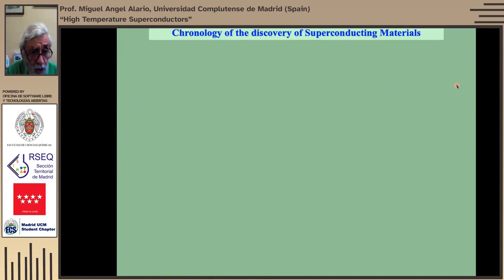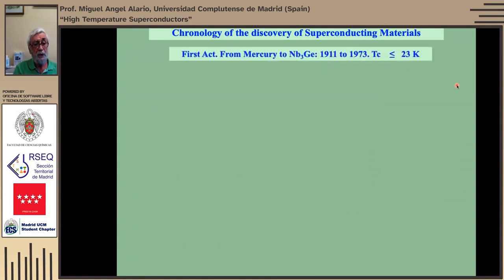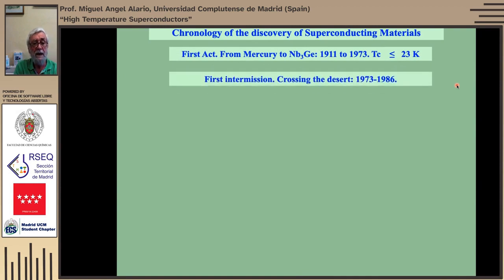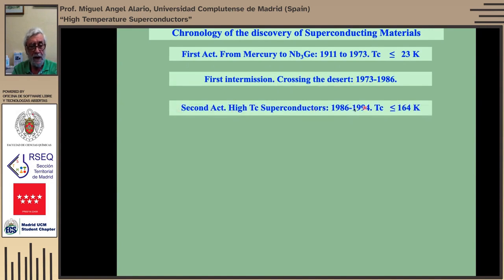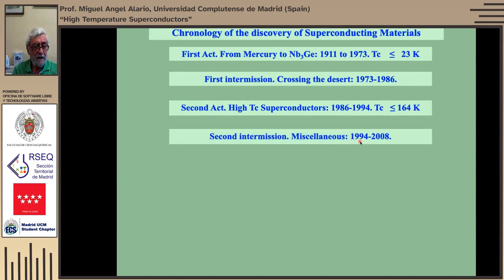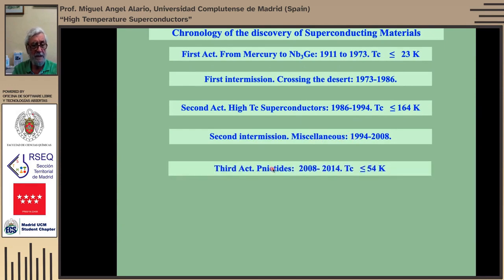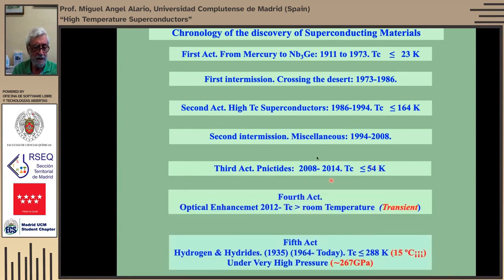So from now, I will make a chronology, the history of the discovery of superconductors. We start from mercury to Nb3Ge, and the maximum TC is 23. Then the first intermission, and not much research here. Then high TC superconductors, and TC gets much higher. Second period with little things, a few, but not many, and not very interesting. Then pnictides, another period. TC is not very high, but an interesting material. Then the fourth act, we arrive at room temperature, but in a transient mode, so only very, very briefly. You can get room temperature, but very briefly. And then, where we are now, we can get to room temperature and beyond, but under very high pressure. So that would be the fifth thing.